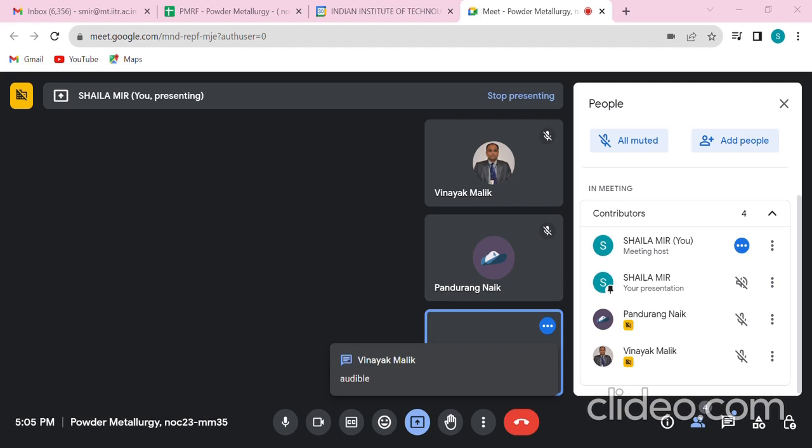The electrolytic cell, where you are trying to deposit any powder from the anode onto the cathode, you would always have a dendritic type of structure. Similarly, if you are having a carbonyl reduction or a precipitation method, the powder shape will be spherical. The atomization will have an irregular type if it is not focused, let's say